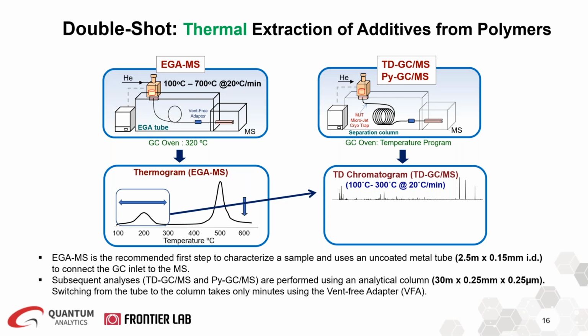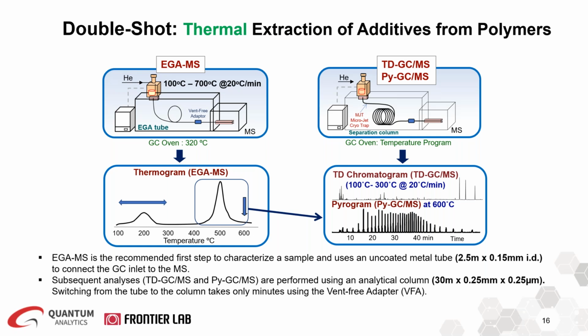that corresponds to any residual solvents, monomers, additives, volatiles, and lighter components. And then the second shot is the flash pyrolysis, where the furnace is programmed at 600 C in this case to analyze the heavier and polymeric compounds from the obtained pyrogram. So this is called a double shot because you are performing two analyses on one single sample, thermal desorption followed by flash pyrolysis.